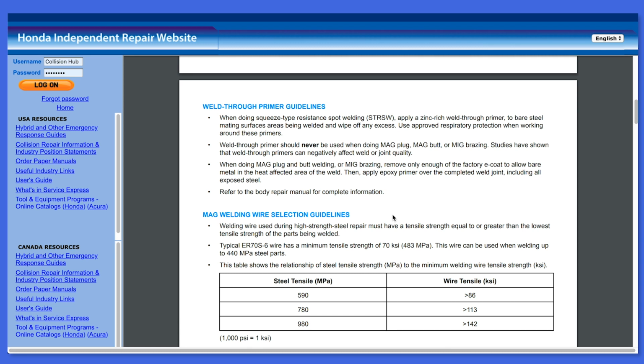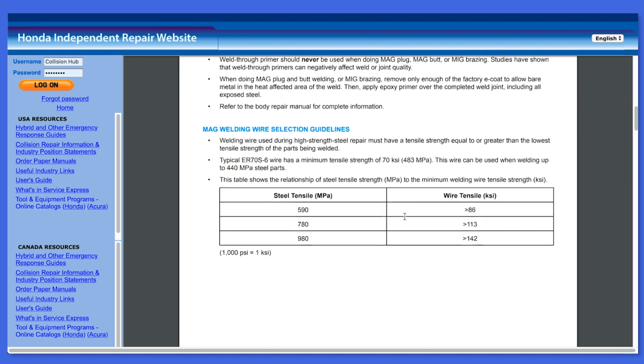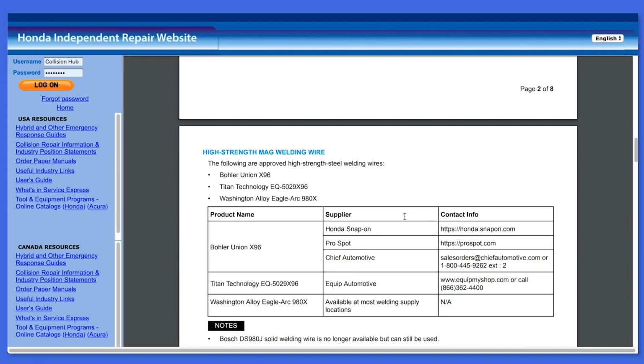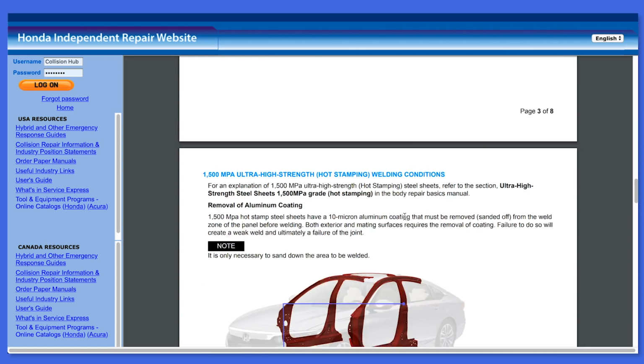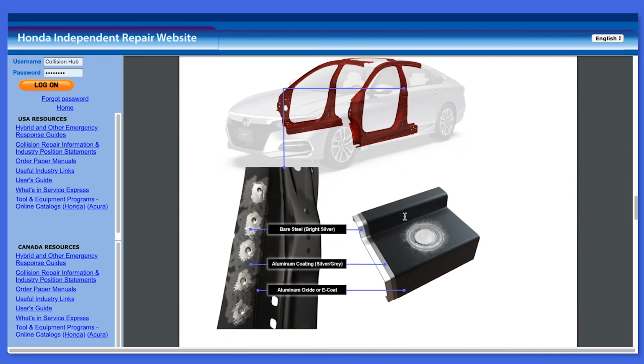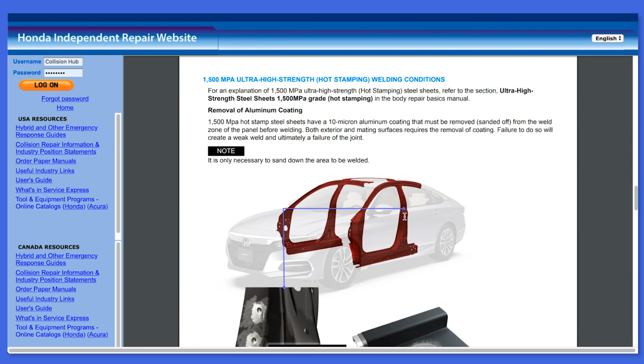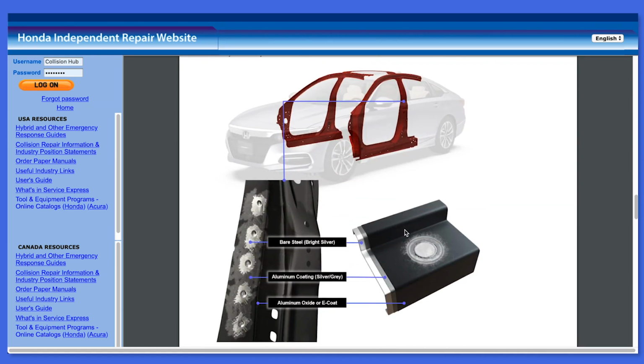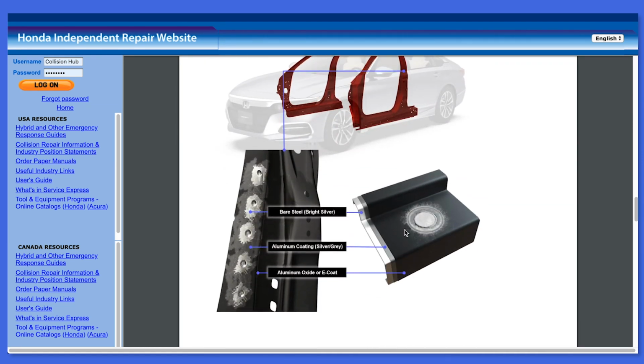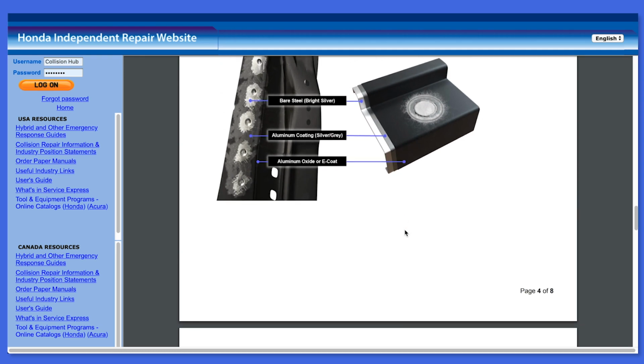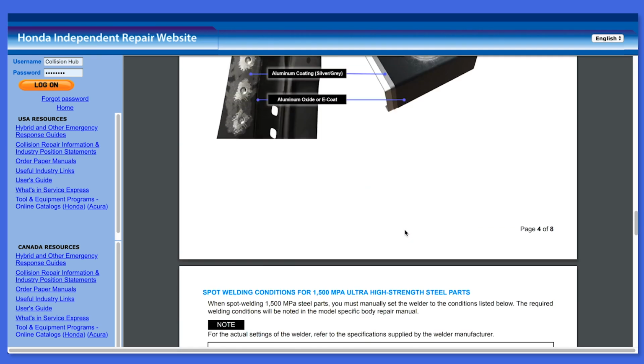But again, Honda is very specific. They want you to use weld through primer on these squeeze type resistance spot welding. If I scroll down a little bit more, I want to point out another feature they've got. Here's our 1500 MPa steel. Again, they want those areas removed completely, so bare steel, not just having that coating still on there, the aluminum oxide or E-coat. They want everything removed from there.